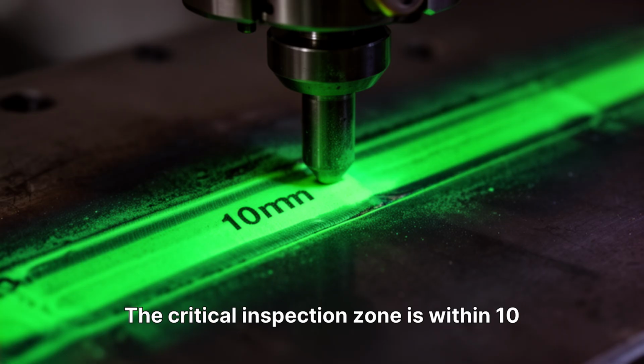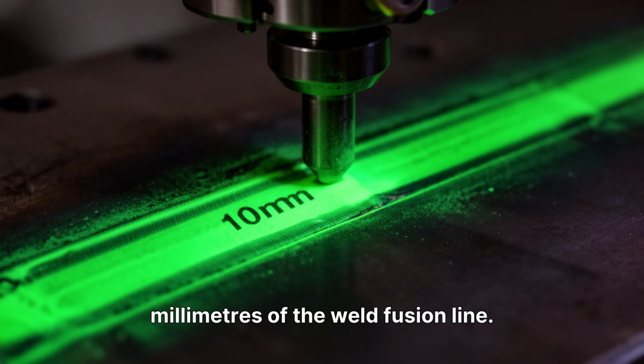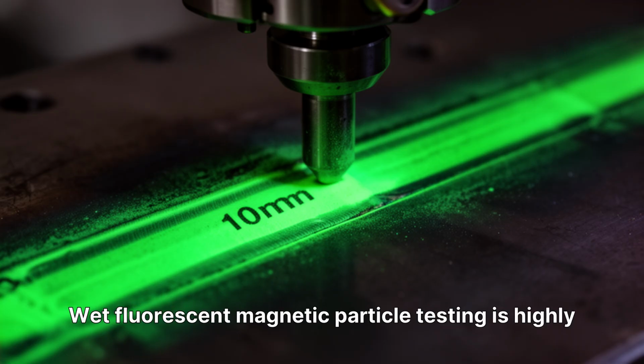Third, SOHIC. Stress-oriented hydrogen-induced cracking concentrates at weld heat-affected zones in sour service environments. The critical inspection zone is within 10 millimeters of the weld fusion line. Wet fluorescent magnetic particle testing is highly effective. All materials in sour service must meet NACE MR0103 requirements. Non-compliant materials are rejection criteria, not just a flag.